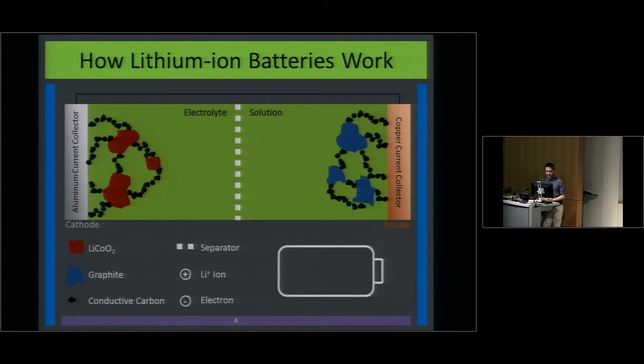And then there's these conductive carbon particles that form a bridge connecting the active material to the current collector, which is where the electrons move back and forth between the two. On the right side, we have the anode with a copper current collector, and the active material there is graphite.